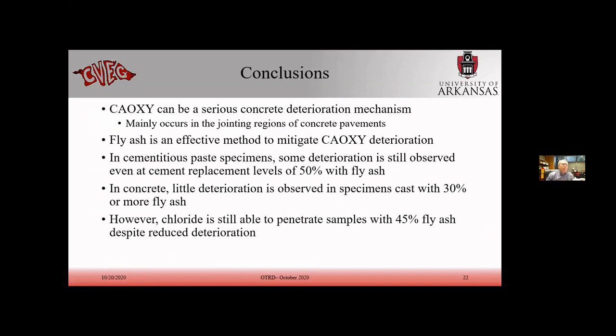So calcium oxychloride can be a serious concrete deterioration mechanism, and it occurs in the jointing regions. We found that fly ash is an effective way to mitigate it. We found some deterioration even with 50% fly ash. In the paste specimens and concrete, we saw a little deterioration at 30% or more, and we did see some chloride ion penetration with 45%.